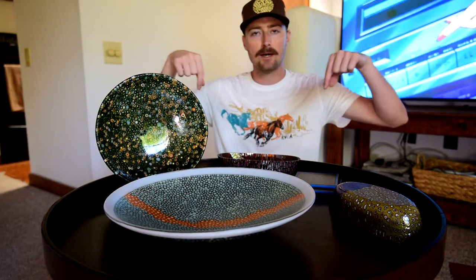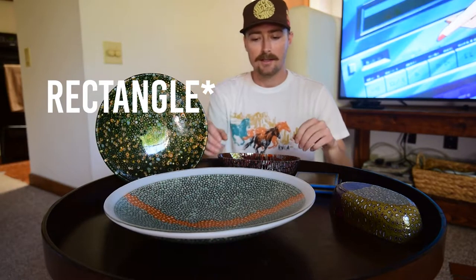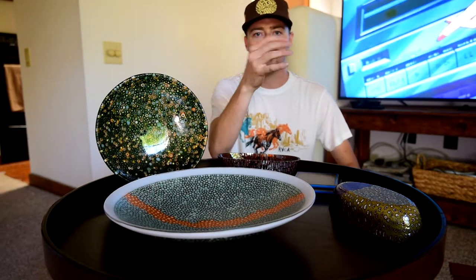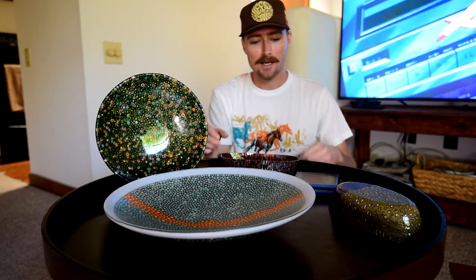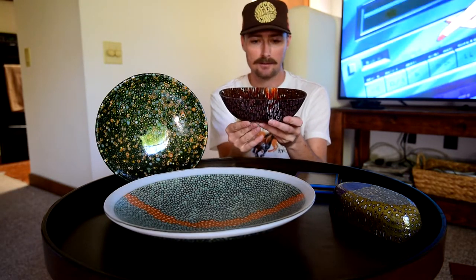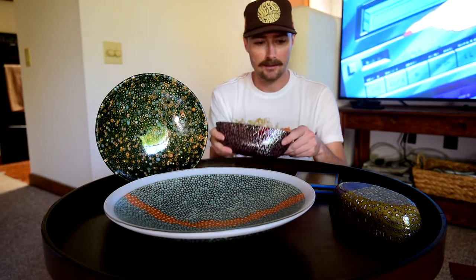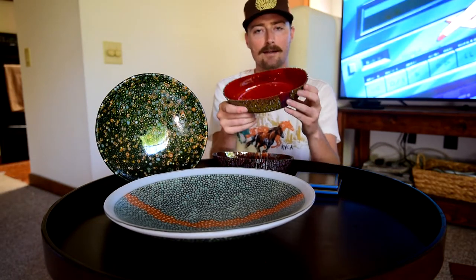So it's a 15 by 8 ceramic mold with about an 8 inch square cut out of the center of it. And when that glass is slumped on top, it's laid on top of the mold, and when it's fired, the glass slowly drops out, and then I cut the rim off, and I'm left with this shallow little canoe-looking shape.